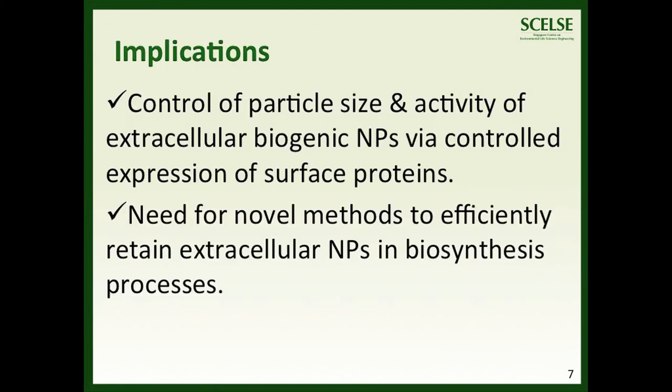Our results suggest that it may be possible to control particle size and activities of extracellular biogenic silver nanoparticles via controlled expression of genes encoding surface proteins. In addition, we also showed that the usually neglected non-cell associated nanoparticles could have high catalytic activity, a finding that highlights the potential for further research effort in this area. Our results underline the need for novel methods such as biofilm that ensure efficient retention of extracellular nanoparticles in biosynthesis processes.